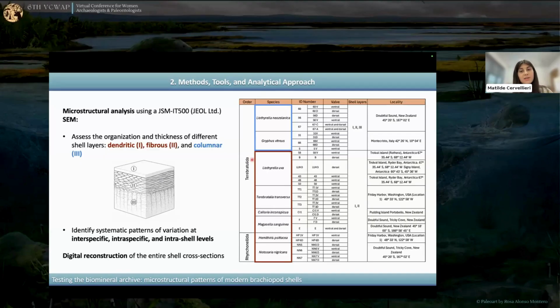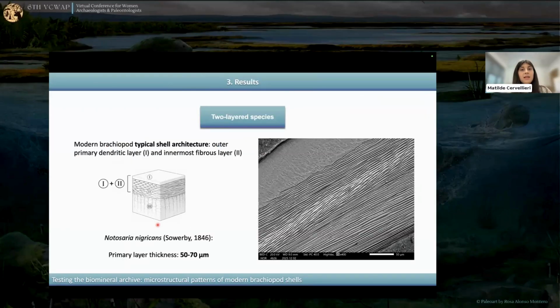For the 2-layer shells, which are here in brown, they develop just the primary and the secondary layer. But there are some species here in bright blue which also develop a tertiary columnar layer. I merged all the SEM images to reconstruct the entire shell cross-sections. And here are the results for the 2-layer species.